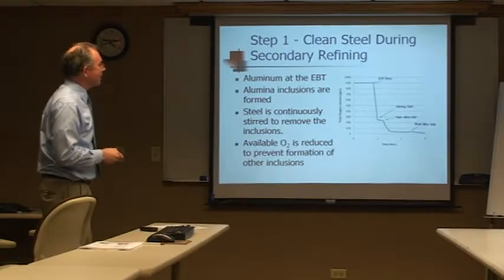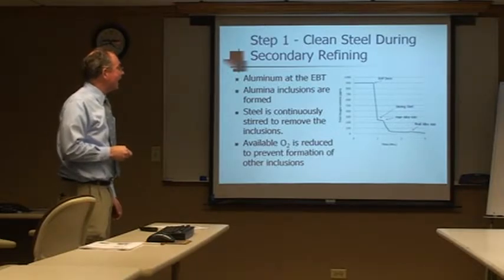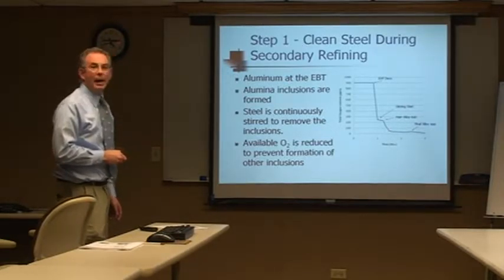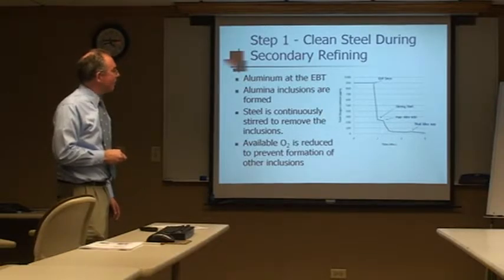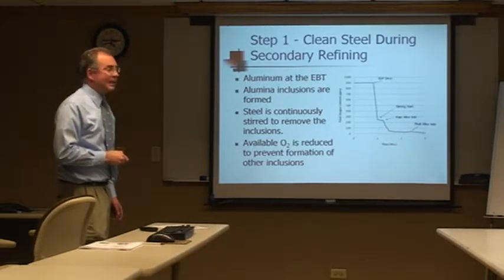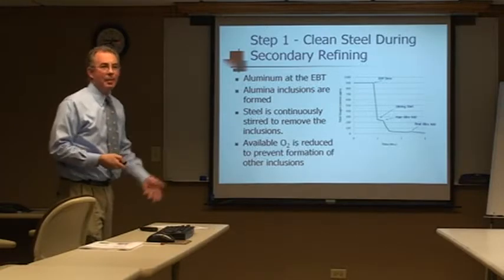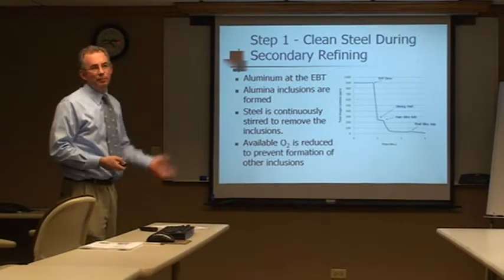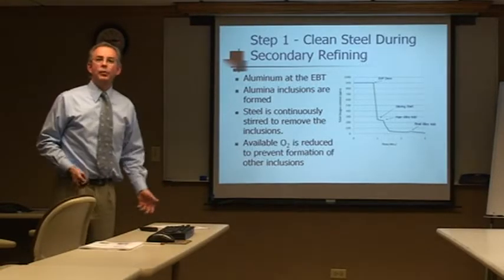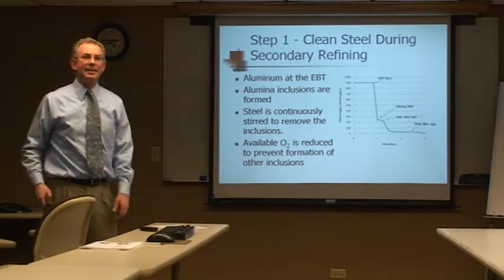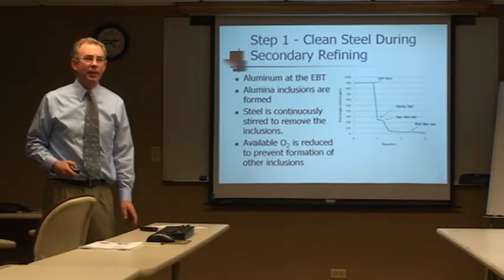Within about the first 10 minutes, we're dropping down to less than 100 ppm. And then by the time we're ready to tap, go to teem, which is about an hour to 2 hours, sometimes longer, we've dropped the aluminum down to less than 10 parts per million.